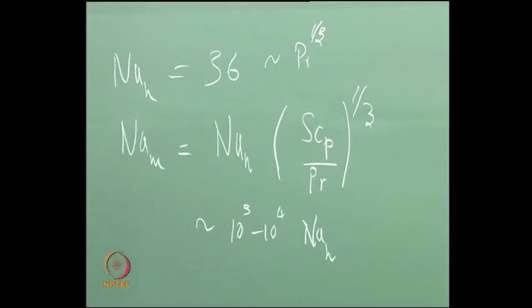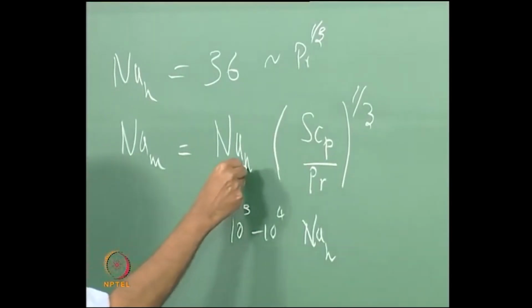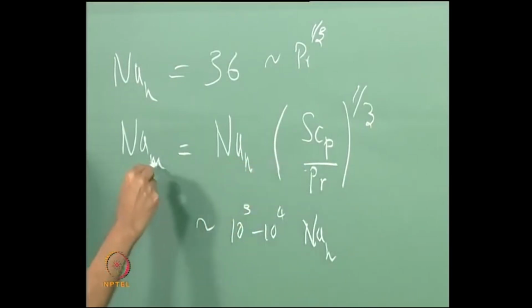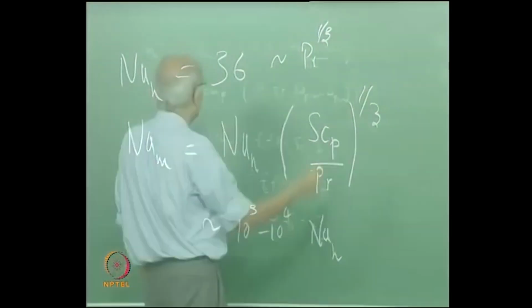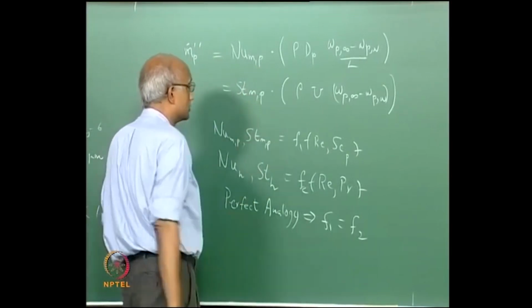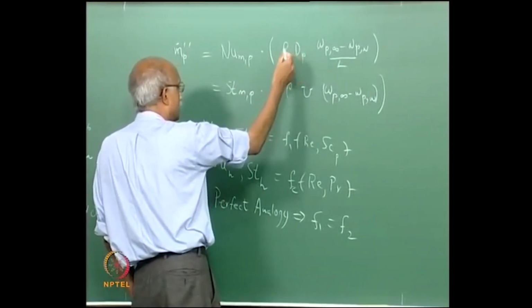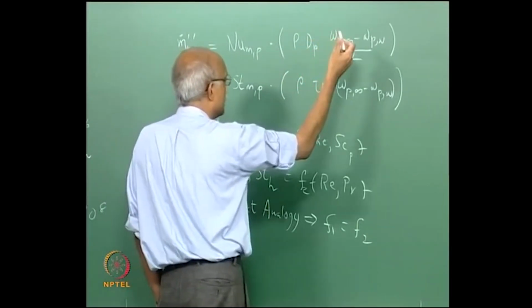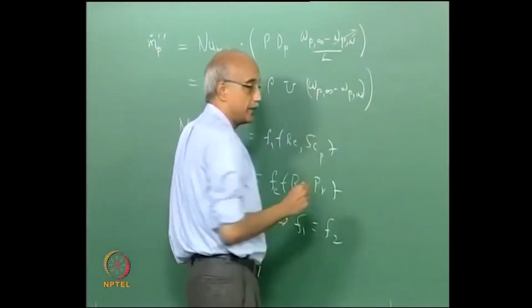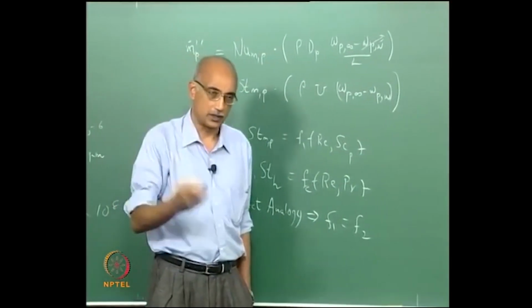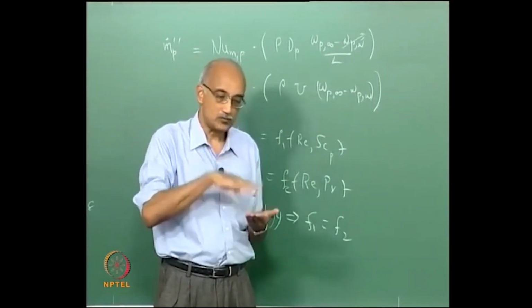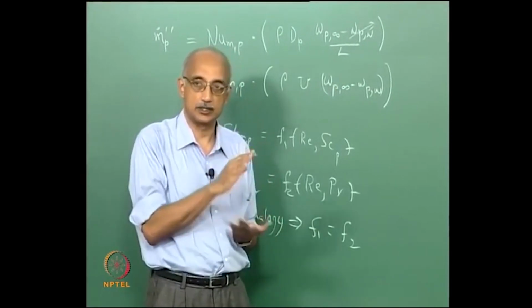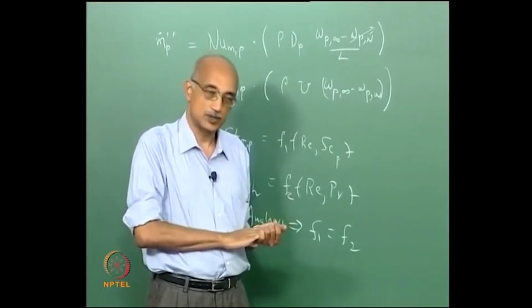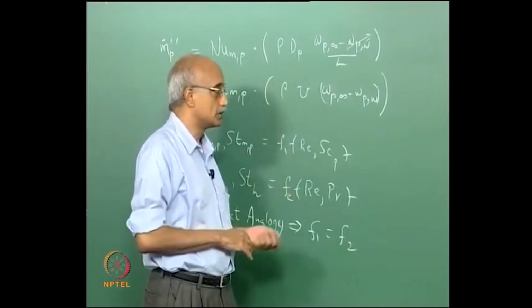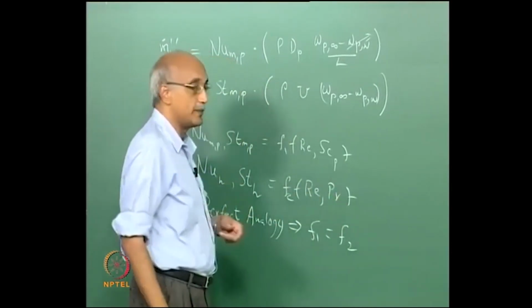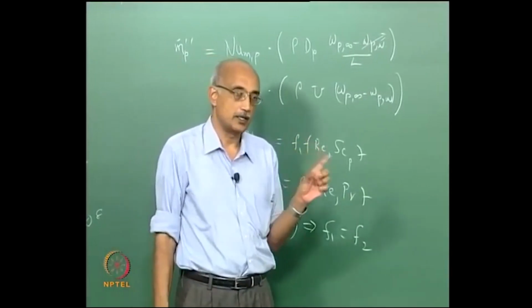So once you know that, once you've calculated the Nusselt number for heat transfer, you apply this formula and calculate the Nusselt number for mass transfer. Then you can go back to this expression and substitute values for density, particle diffusivity. For the most part, you can assume that omega pW is much smaller than omega p infinity. In other words, the particle mass fraction far away from the deposition surface is much greater than the particle mass fraction near the deposition surface, and so you can proceed to calculate your MP dot double prime values and divide it by the area of the tube.